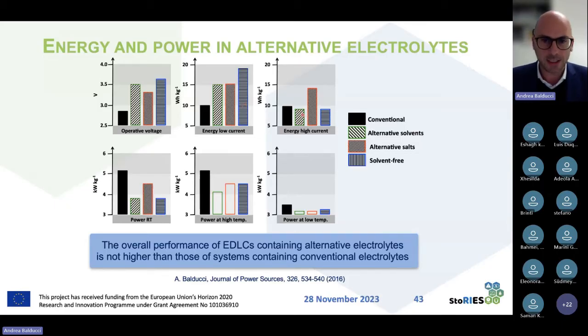And what we can see here is that when we apply high current, we are talking about ampere per gram, for example, 1 or 10 ampere per gram, to give you an idea. Well, then at the end, what is happening is that the energy that we are getting out of the system containing alternative electrolyte is not higher than that of the state of the art. Why is this the case?